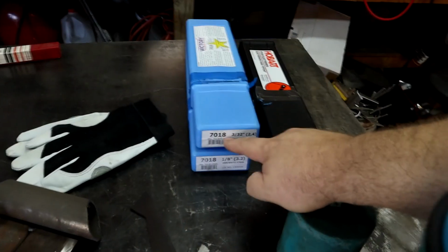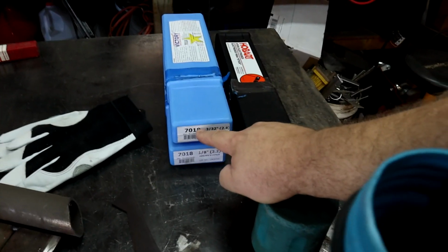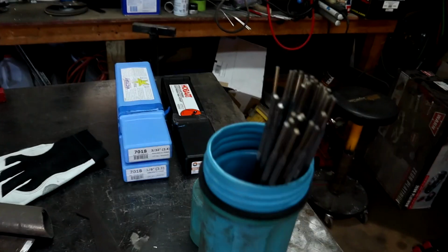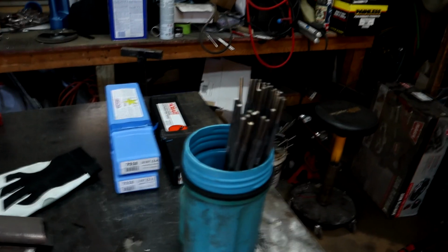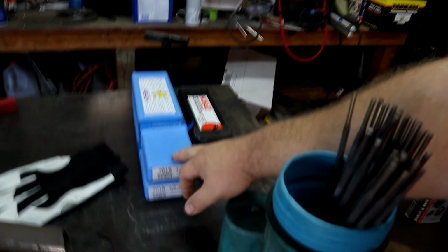One thing, particularly about 7018 or low hydrogen electrodes, is they do need to be kept airtight in a hermetically sealed environment, so no moisture gets into them. No electrodes like to be wet or have oil on them, but 7018 is pretty particular to high humidity.